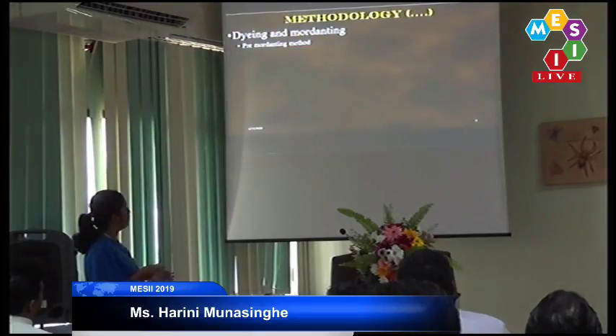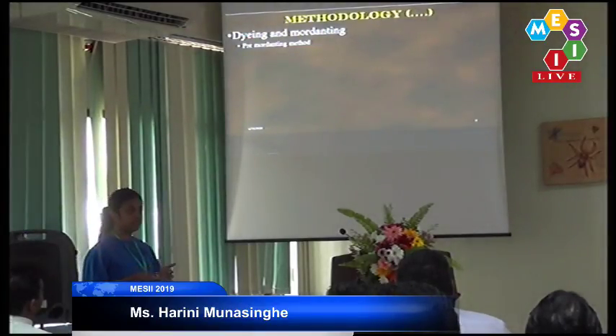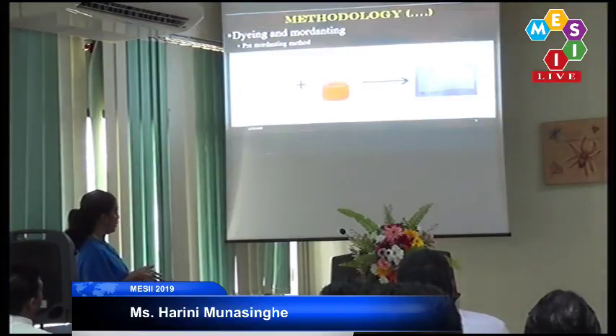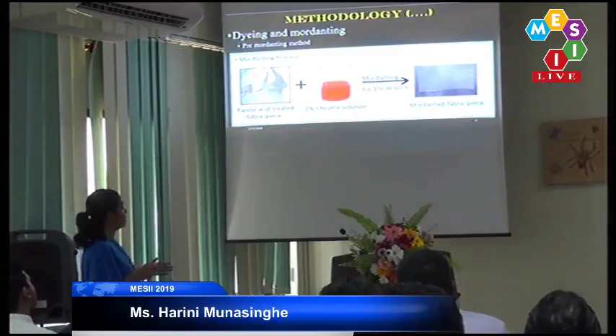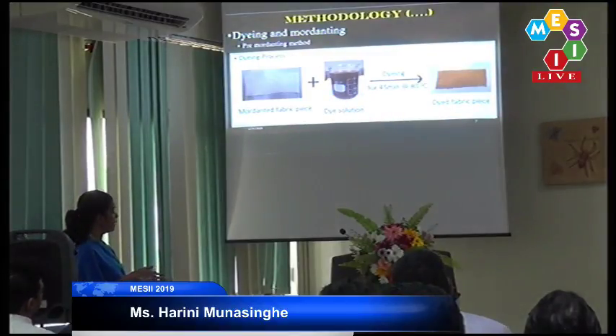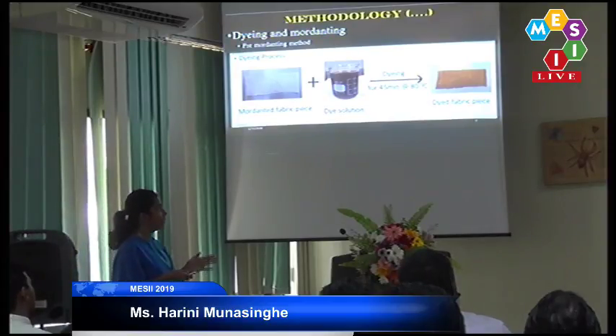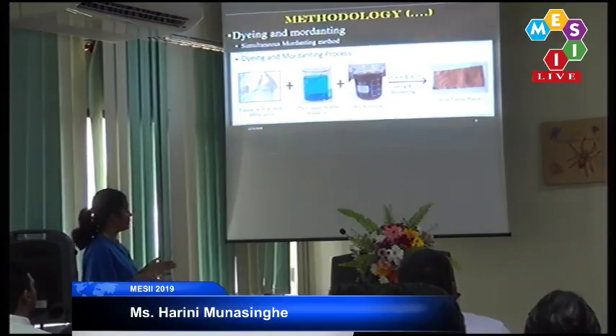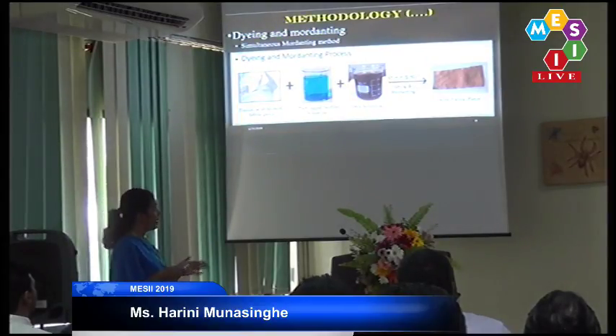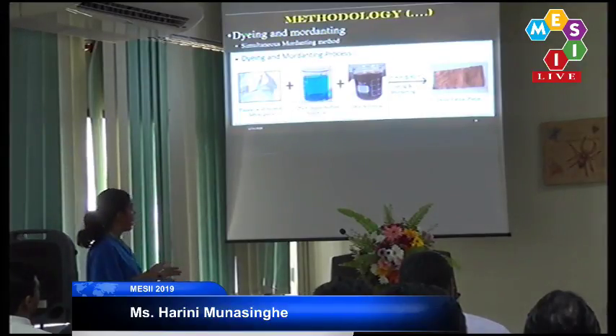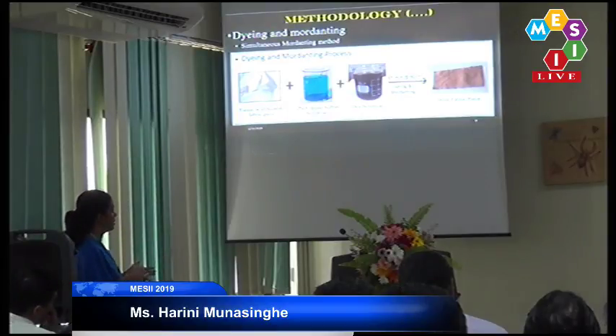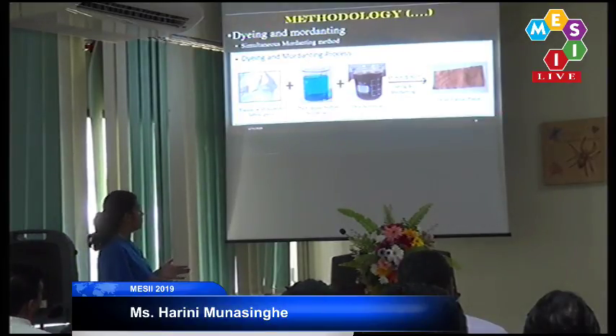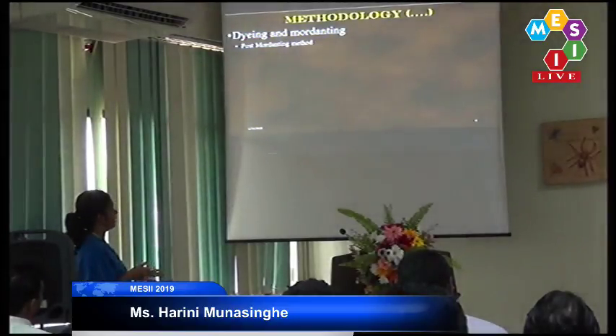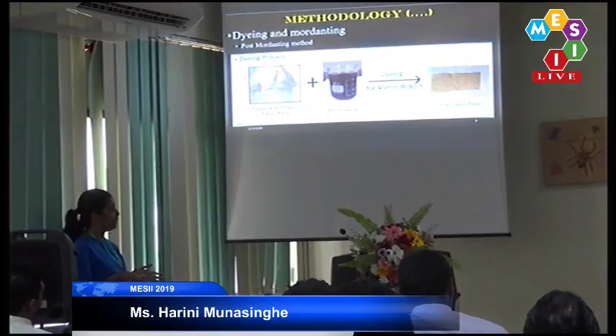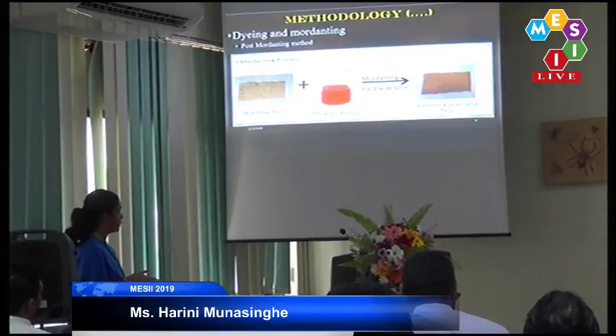And also after that, we did the mordanting process under 3 different mordanting methods. The first one is the pre-mordanting method. Here we first did the mordanting process using the tannic acid treated fabric piece. Then we did the dyeing process for the mordanted fabric piece and obtained the dyed fabric piece. The second method is the simultaneous mordanting method. Here, instead of doing the dyeing and mordanting processes separately, we did the dyeing and the mordanting process at the same time for the tannic acid treated fabric piece and obtained the dyed fabric piece. The third method is the post-mordanting method. Here first we did the dyeing process, then we did the mordanting process for the dyed fabric piece and obtained the mordanted dyed fabric piece.